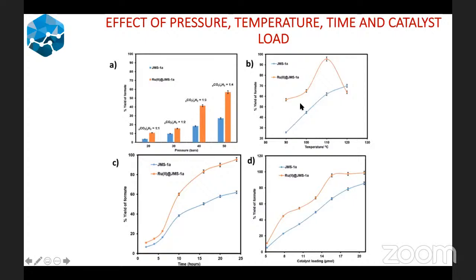And as you can see here, at about 110 degrees, that's the optimum temperature for the ruthenium functionalized MOF. Beyond 110 degrees, you can see a drastic decrease in the yield of formate that is produced. This can be attributed to the decomposition of formate at high temperature. Remember, this is an exothermic reaction that is taking place. Formation of formic acid is an exothermic reaction.